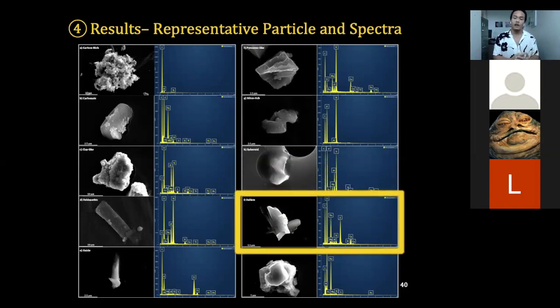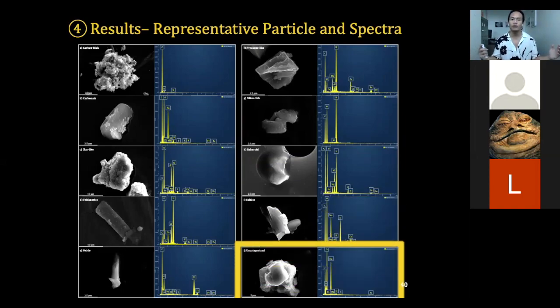The sulfates are particles that have a high sulfur peak, just like this one. And as you can see, all the other particles barely have any sulfur peaks. And this one has a sulfur peak, which again was only found in the post-Kilauea eruption filter. And then if we had just no clue what they are based on spectra or morphology, we lump them in an uncategorized category, such as this one in the yellow box.